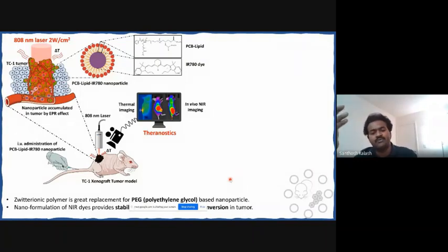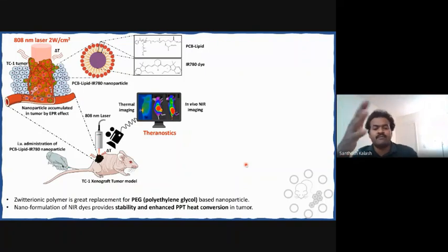PEG is a widely used polymer for nanoparticles for antifouling, or for preventing any type of protein corona formation. But PEG itself has some issues nowadays, because it can also generate antibodies when you do a second injection. So nowadays PEG is a material that is increasingly being replaced with other types of nanomaterials. Zwitterionic polymers are one of them. And more important from this study, we also found that this nanoparticle formulation increases the stability of the dye and also enhances the photothermal heat conversion in the tumor.